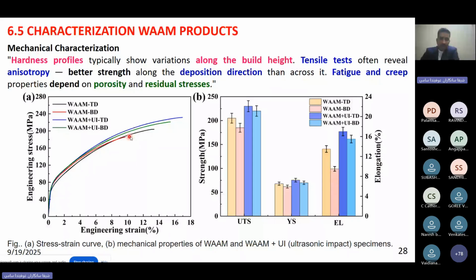And this is after ultrasonic impact, you can see how much the strength is improved. The same materials, but they introduced ultrasonic impact followed by the deposition. You can compare this one here, almost 190 or 180 megapascals, but here in the build direction, I think 220 something. So this much strength can be improved. That's what the slide shows.